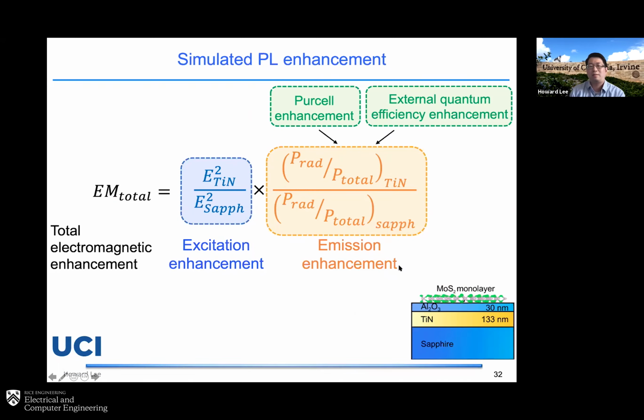And the emission enhancement basically is telling you how much the emission decay rate will change if you're collecting at a certain angle of collection by monitoring in the far field. So it will be related to the Purcell factor enhancement and also the external quantum efficiency enhancement. Basically, it's a quantity telling you how much emission enhancement you have. Combining those, you can calculate the total electromagnetic enhancement.